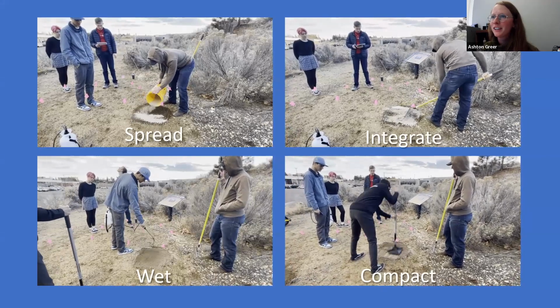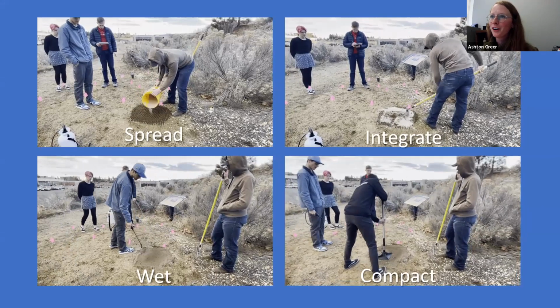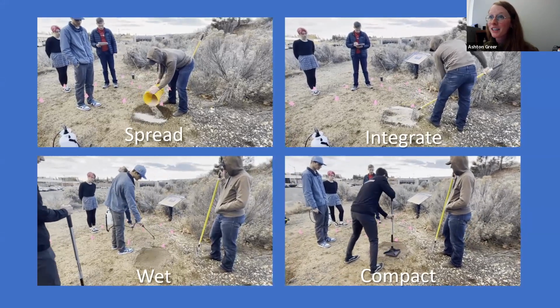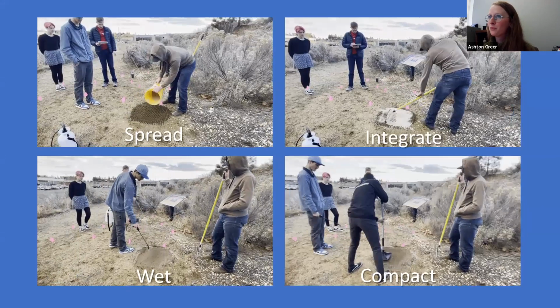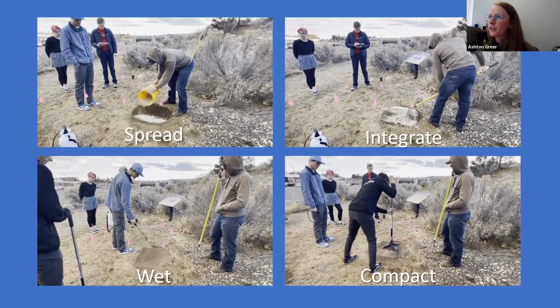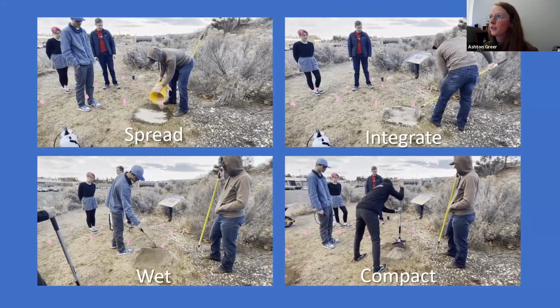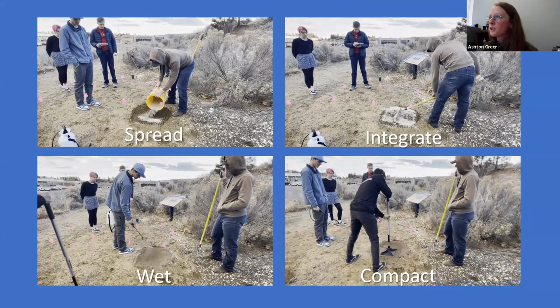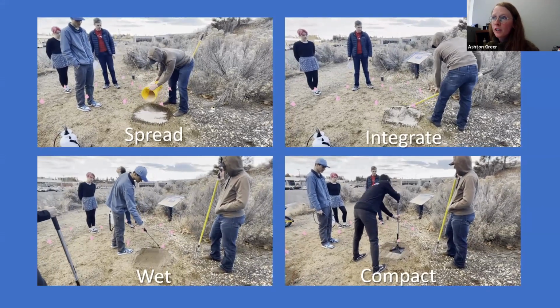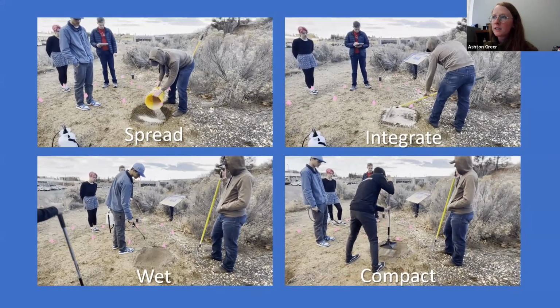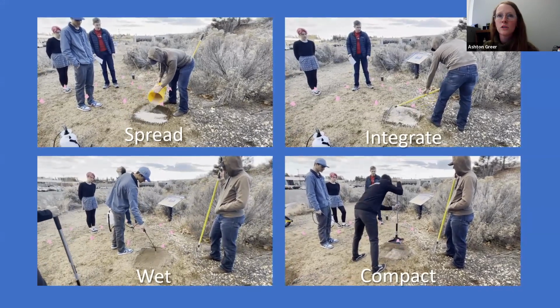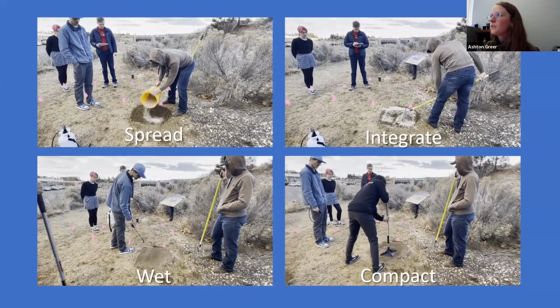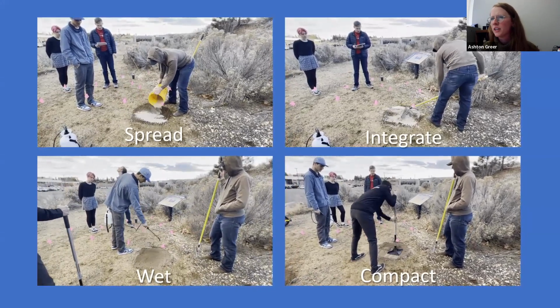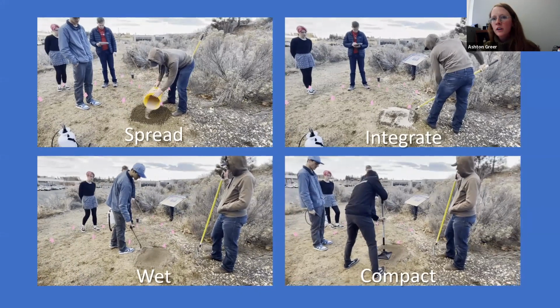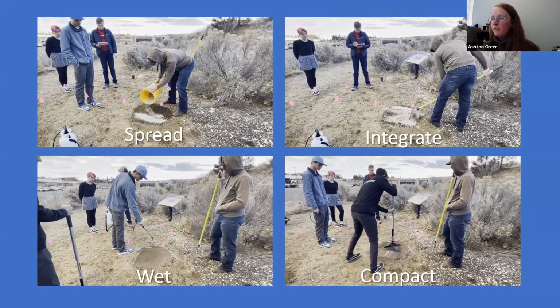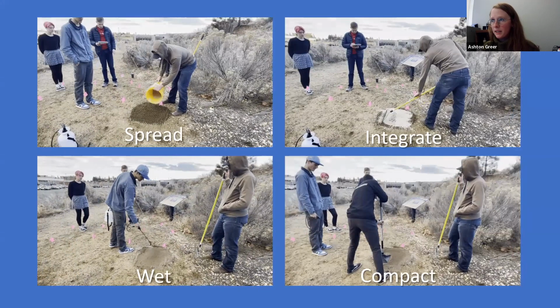So our students are really kind of the chefs in the kitchen for a lot of this. I probably can't emphasize enough how much they have contributed to this work. So here you can see some of our students helping us apply some small test patches. In that first figure, they're applying a pre-mixed ash cement mix to the surface in its dry form. And then in step 2, they're raking it in an attempt to integrate it with the in situ soil. Third, they're adding moisture, and then they're finally compacting it with a plate tamper.